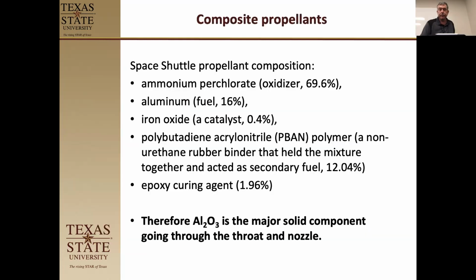So, what goes into the shuttle propellant here? This is by weight. It's about 70% ammonium perchlorate by weight, 16% aluminum metal. Then a catalyst, a combustion catalyst, iron oxide. Butadiene acrylonitrile rubber is about 12%, and then the epoxy curing agent for this.